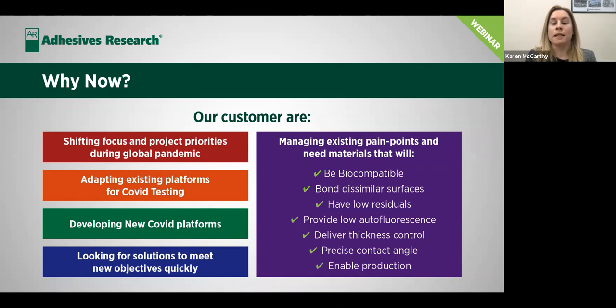Also looking to bond dissimilar surfaces. So depending on the device, you could have a low surface energy substrate and a high surface energy substrate, and it can be difficult to bond these two surfaces together with one adhesive. So the solution here would be to use a double-sided adhesive with a low surface energy adhesive on one side, such as a silicone adhesive to bond to the low surface energy plastic, and a high surface energy adhesive on the opposing side to bond to the high surface energy substrate of your device.